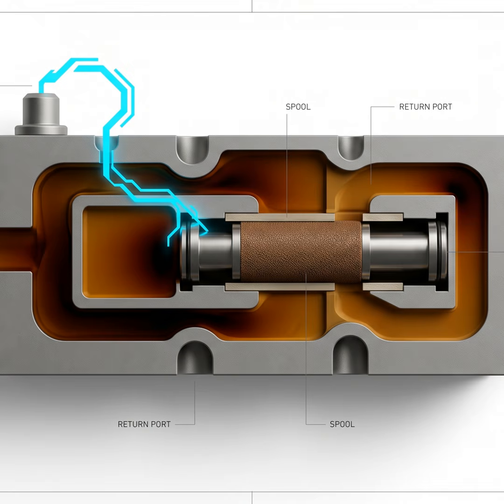In this specific case study, the technicians were battling a chronic, dangerous problem, severe polymer leakage. The machine was leaking 20 to 100 milliliters of molten ABS plastic per hour. That sounds like an absolute nightmare. Not only is it a mess, but molten plastic under high pressure is incredibly dangerous to the operators. Where exactly was it leaking from? The massive leakage occurred right at the junction between the machine's nozzle and the mold's sprue bushing. This is the critical high-pressure transition point where the molten plastic leaves the machine's heating barrel and is forced into the heavy steel mold. And what caused it? The leakage was a compounded failure caused by severe seal wear, an extreme injection pressure of 150 megapascals, and high ambient factory temperatures.